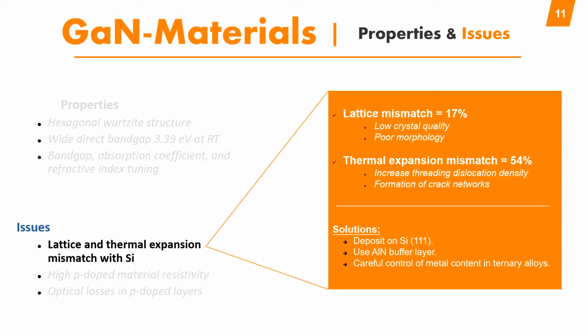Also, good and careful control of metal concentration in ternary alloys, such as aluminum gallium nitride, as we said, can be used so that we can compensate the tensile strain that is created in the gallium nitride layer after deposition by a compressive strain which is induced in the layer, and then reduce the bowing probability.